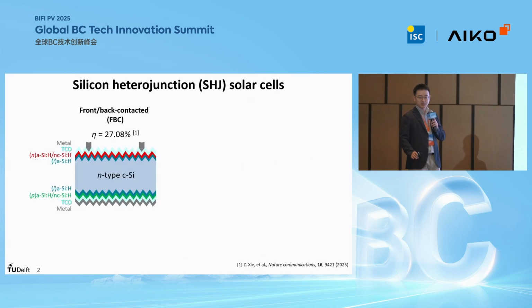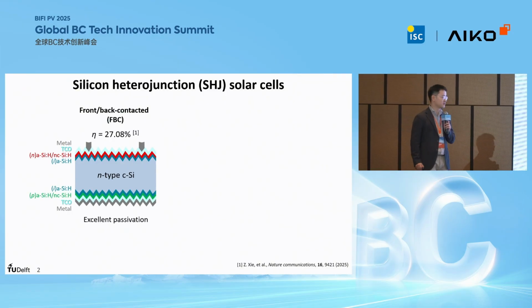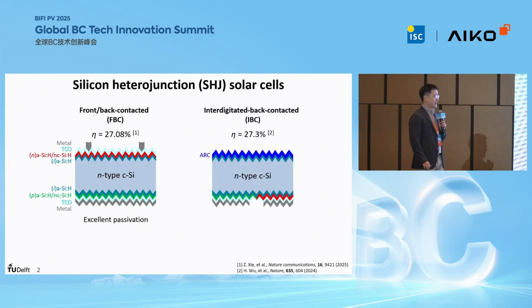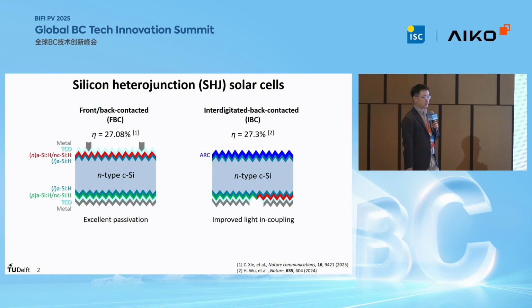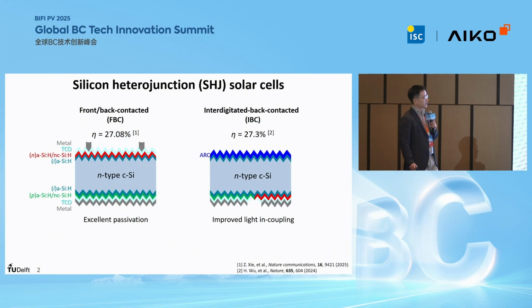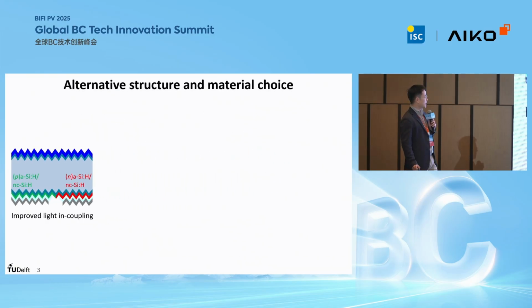Front-back contact silicon heterojunction solar cells have already demonstrated efficiency over 27%, and this is mainly thanks to their excellent surface passivation. And this efficiency is further boosted to well above 27% in the IBC configuration, mainly due to the improved light incoupling. In a typical IBC solar cell design, both N-type and P-type contacts need to be patterned, which results in a relatively lengthy fabrication process.